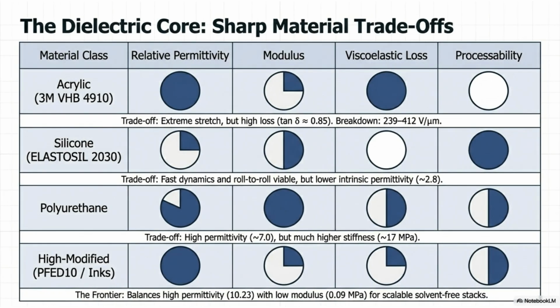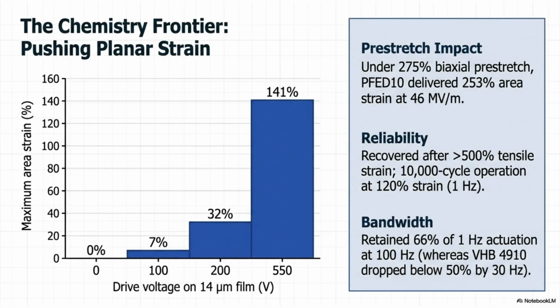Material choice presents sharp trade-offs. Acrylic offers extreme stretch but high loss. Silicone allows fast dynamics but has lower permittivity. Polyurethane has high permittivity but is much stiffer. High modified materials balance high permittivity with low modulus. Pushing planar strain is the chemistry frontier. PFED-10 delivered significant area strain under biaxial pre-stretch and maintained good reliability and bandwidth, showing strong performance compared to other materials.